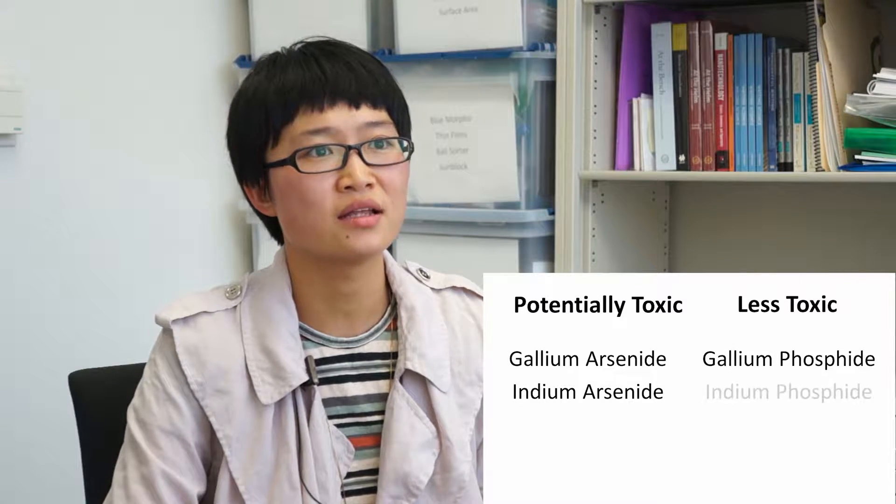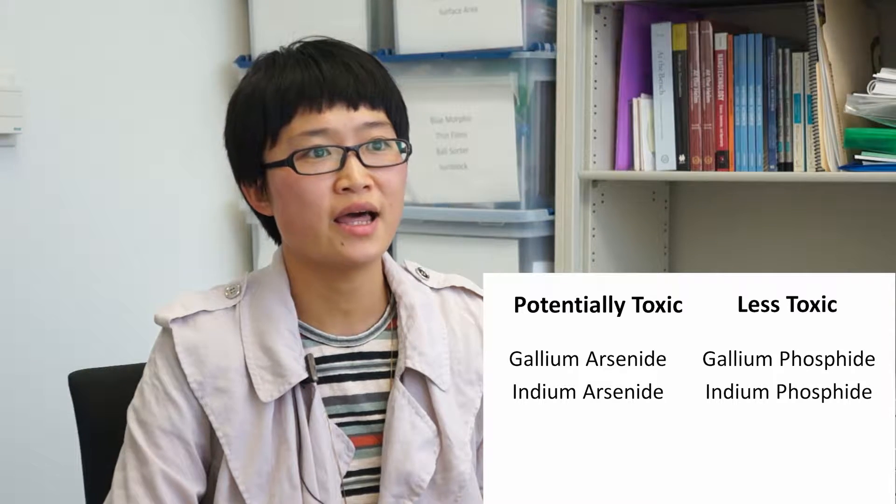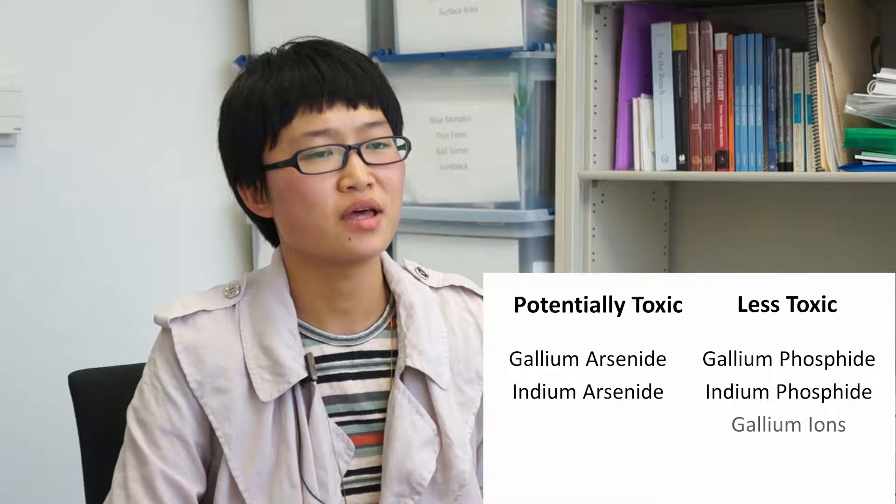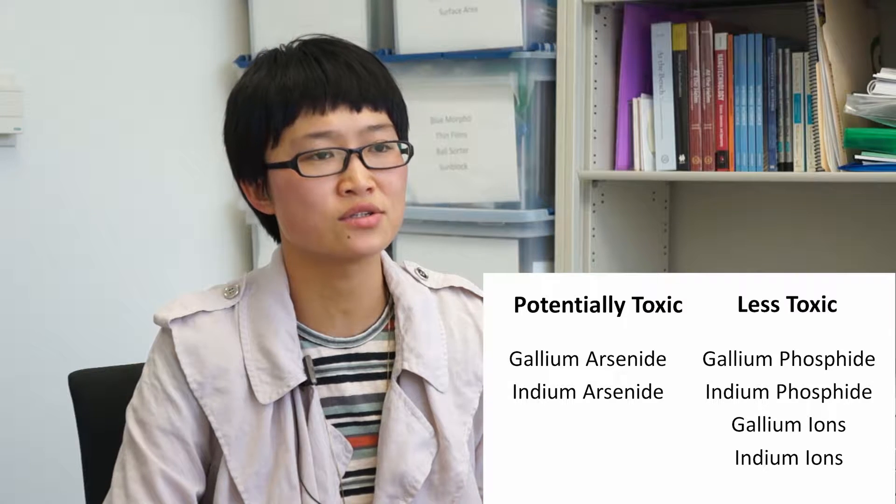gallium phosphide and indium phosphide particulates were substantially less hazardous. For the ionic form, gallium and indium ions were also substantially less hazardous,